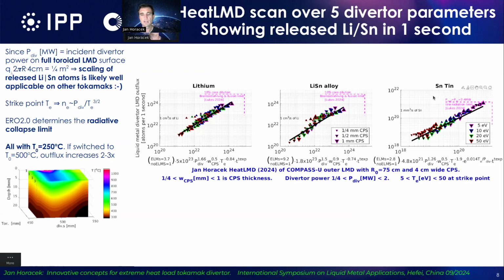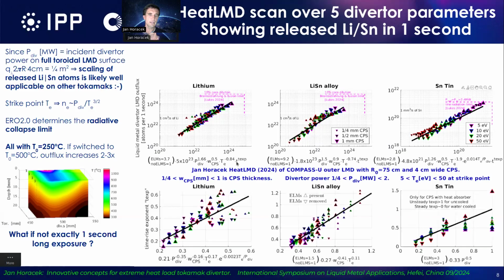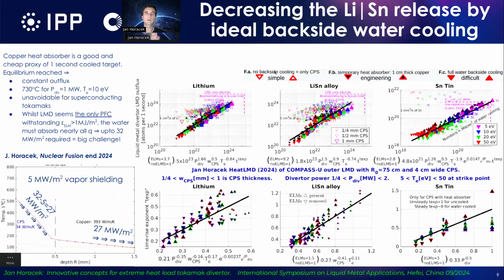And also I vary the way I cool down the backside of the target, because here is the capillary pore structure with lithium-tin. And then there is copper below it, which cools it down. And this is very important, especially for 1 second plasma. But if the plasma is not exactly 1 second long, then you have to include this additional multiplication factor by time with this exponent. This exponent, unfortunately, is not a constant, but it's about half or somewhere around it, depending on the plasma parameters. So it rises nearly linearly or even more. But it also depends on what kind of cooling you imagine.